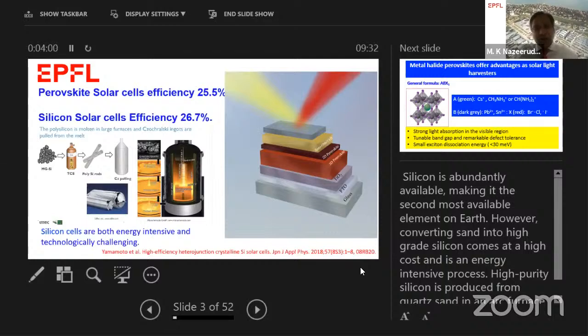On the top, we have a contact. Now, by shining light, we get the charges out and we collect electricity. At the same time, if we inject carriers into the perovskite material, we can get emission coming from this material, band gap emission. You can tune these emission properties by changing different cations or anions, as you will see in the next slide.